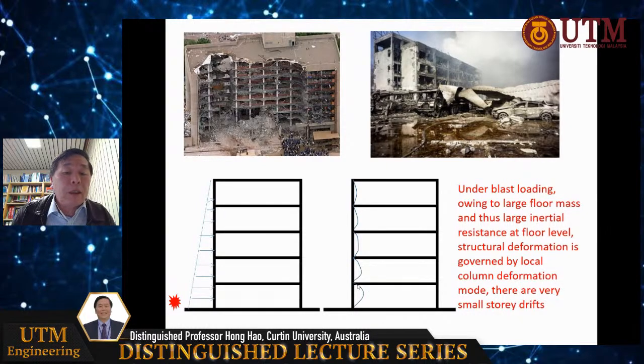So this big mass provides a large inertial resistance, so the deformation damage is at the column. If you lose one column, a bottom column for example, it will trigger progressive collapse. That is how damage occurs in blast loading. That explains why this building, although it partially collapsed, still stands almost vertically. You don't see any drifts.